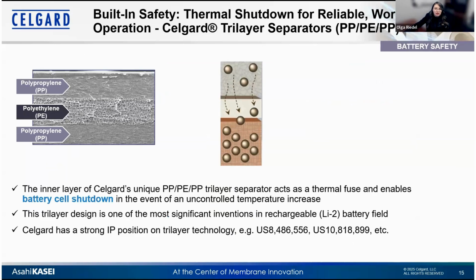But as mentioned, ceramic coatings are often a solution to increase safety. And on the other hand, I also just mentioned that we can reduce cost by going to only a PP solution. So let's talk about Trilayers for a moment, because Trilayers are our solution for cost-efficient safety in energy storage systems. Celgard Trilayers consist of polypropylene outer layers and a polyethylene middle layer. Since the polyethylene has a significantly lower melting point, namely at around 130 to about 135 degrees C, versus 160 degrees C for polypropylene, the polyethylene layer actually acts as a thermal fuse, so provides low temperature shutdown. So during any safety incident, the pores are closing and the current is being cut off.